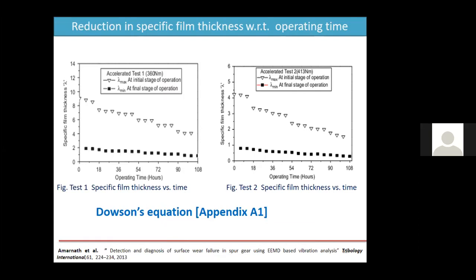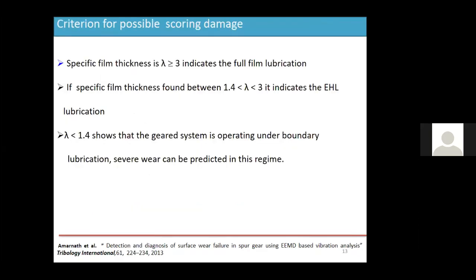For both cases, the specific film thickness is decreasing in this fashion. By using this, you can get the details of scoring damage. If lambda is greater than 3, then the scoring is minimum. It is under the full film lubrication regime. Almost no wear happens here, or very negligible wear happens during this full film lubrication regime.